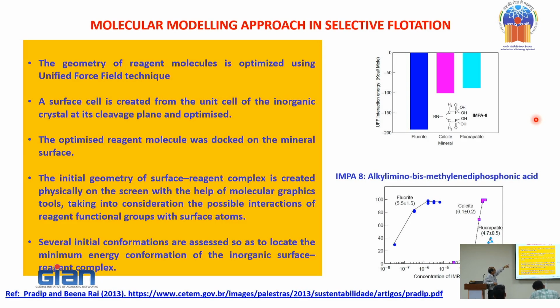A surface cell is again created from the unit cell of the inorganic crystal at its cleavage plane. See, there will be different cleavage planes in a crystal, 100, 010, 001, all those things. And every mineral has got one cleavage plane only across which the grinding takes place. Once you grind it, maybe predominantly 100 will be present, or 010 may be present, or 001 may be present. So there is a preferential cleavage plane. So you first decipher that. Now you know the surface disposition of different metal ions and the inter distances between each metal ion in that particular cleavage plane. So that is the optimized cleavage plane of that mineral crystal, and you have the optimized structure of the reagent molecule.